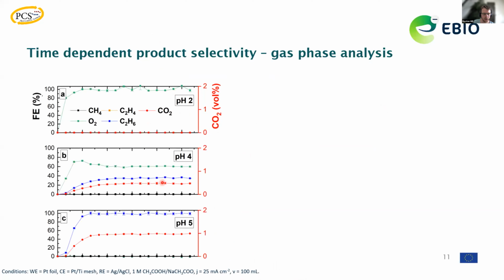So if we then go to the intermediate regime of pH 4 and 5, we already could see that there are gas phase products following the Kolbe processes formed, especially at pH 5. We got 100% Faraday efficiency to ethane. And also point out that there's quite some CO2 evolution here, which is in agreement with the Kolbe scheme that I've shown you before. But what was surprising here is that at pH 4, we already have quite some ethane formation, which is stabilizing after a certain period of time. And we have concomitant oxygen and ethane evolution occurring at pH 4.